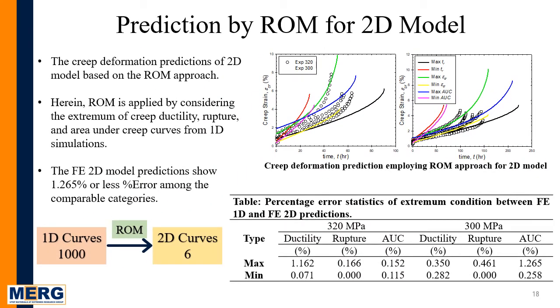Deformation prediction of the 2D model based on the ROM approach is shown. We take the extremum cases of ductility, rupture, and the area under the creep curves from the 1D model. Those material constants and the testing conditions are retrieved from the input deck and applied for the 2D model, and the predictions are conducted. The FE 2D model predictions show the error between the rupture, ductility, and area under creep curves as low as 1.265% or less. But the most meaningful part of this study is that we are reducing those 1000 1D model creep curves to just 6 2D model creep curves.